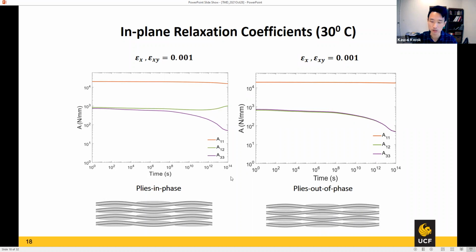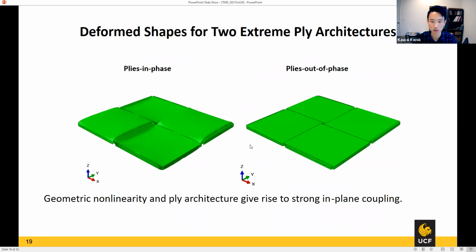That is quite interesting to us: by changing the ply configuration, you actually get different behavior in coupling. The reason for that is geometric nonlinearity. If you have all the plies in phase, and then you stretch it, all the waves are going to deform in the same way through the thickness, and it's going to squeeze the laminate in the transverse direction more, and they're always reinforcing that change. On the left-hand side, this is just a deformed shape. I'm trying to show you that you get a more extreme curved shape in the transverse direction as you stretch in the loading direction. That is the case for the in-phase configuration.